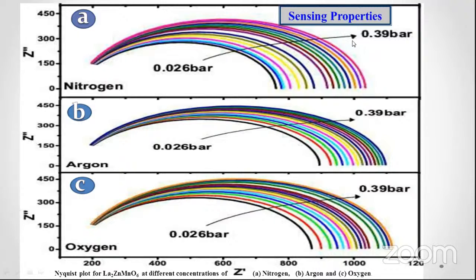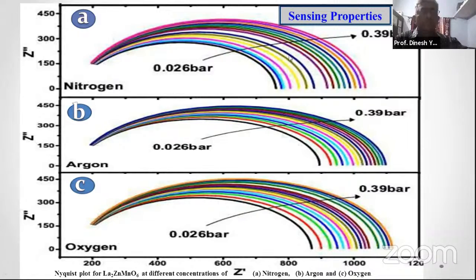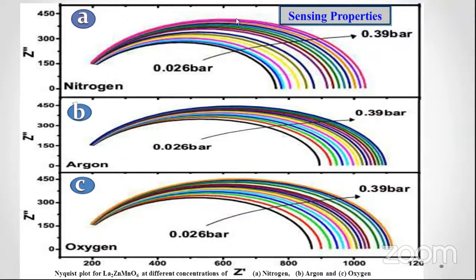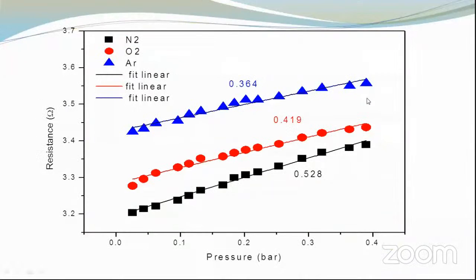So we have purged different gases here. The sample is mounted in the cold head of a closed cycle refrigerator, where in addition to temperature variation, the sample chamber may be purged by various gases at different concentration, or you can say pressure. After the gas is purged, the sample is left for a waiting period of 15 minutes before each measurement for homogenization of absorption. Here, with the increase in pressure, the semicircle radius increases. With the help of the intercept on the x-axis, we have plotted the resistance versus pressure. Here we get different slopes.